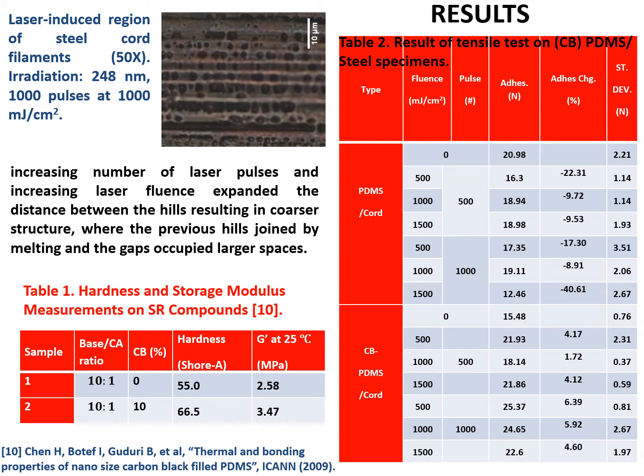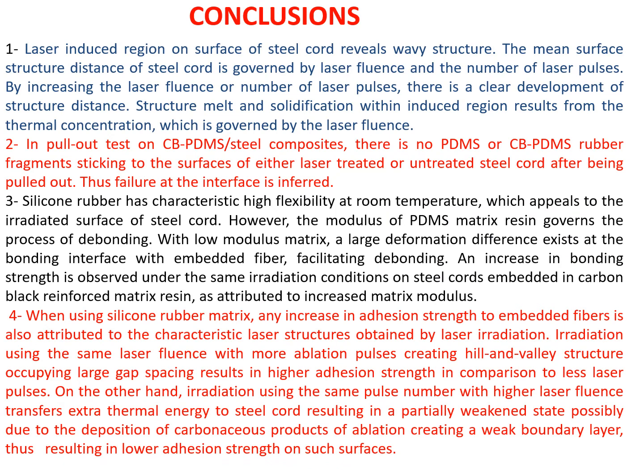The results with the neat resin PDMS cord composite were not as well behaved, as shown on the upper part of the table, even though we still see some increase in adhesion when we increase the number of pulses and fluence. In conclusion, we can say that the laser-induced region on the surface of the steel cord reveals wavy structures. The mean surface structure distance of the steel cord is governed by laser fluence and the number of laser pulses. By increasing the laser fluence or number of laser pulses, there is a clear development of structure distance. Structure melt and solidification within the induced region result from the thermal concentration, which is governed by the laser fluence.